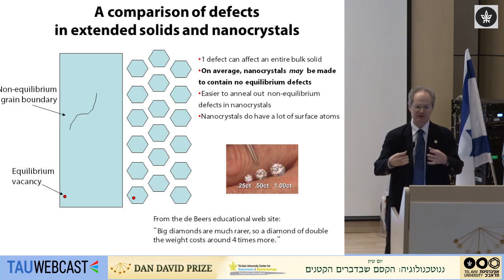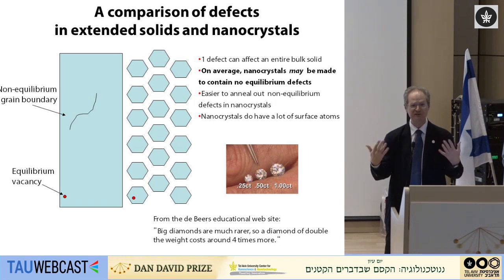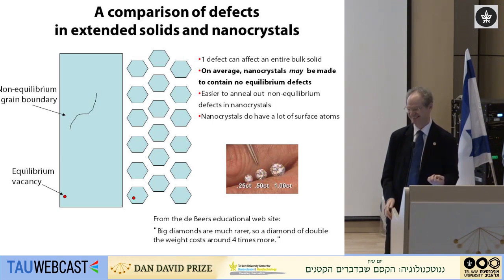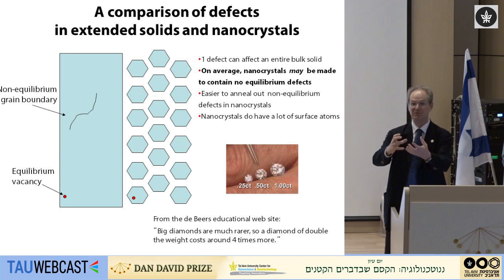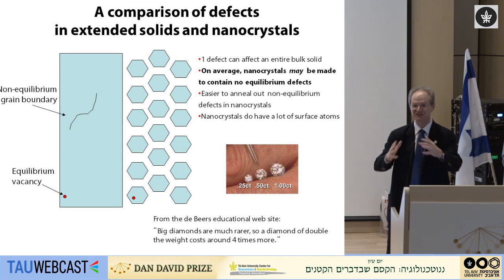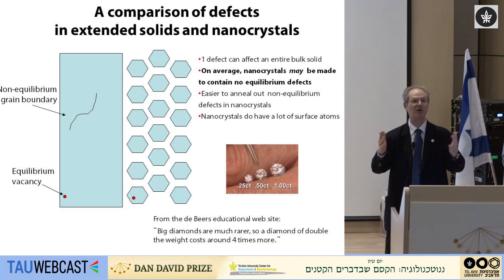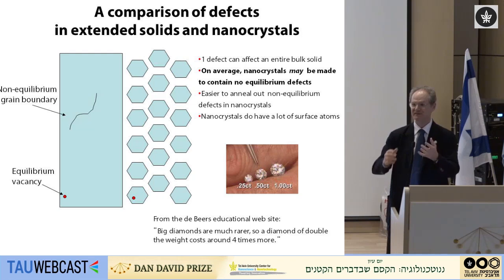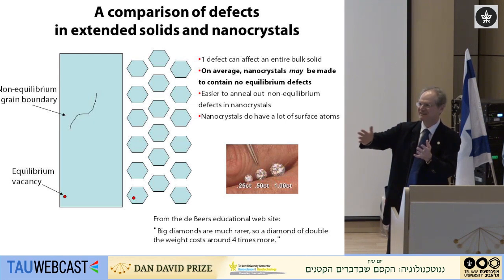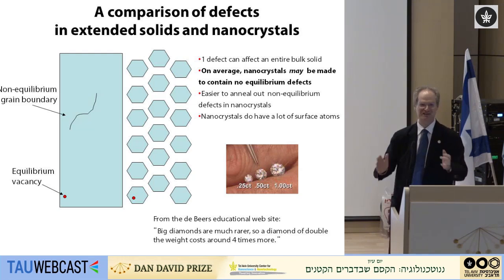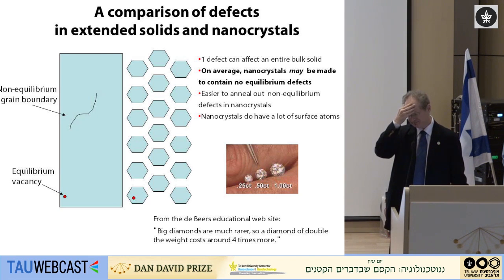But why is that? That's because you want to buy a crystal of high quality. That determines its optical purity. And imagine now that you have a crystal which in the course of its growth, somehow a mistake has occurred. Typically they happen. And so at some point there is an error inside this crystal that ruins its optical properties. And now you would like for it to go away. Well, it will eventually go away. It turns out the time scale is exponential with volume. So as a crystal becomes larger and larger, the probability that a defect will eventually work its way out depends so strongly upon the size. And the consequence of that is that the diamond becomes very rare when it's large and high quality at the same time. It's unusual to find, and it's difficult to make.